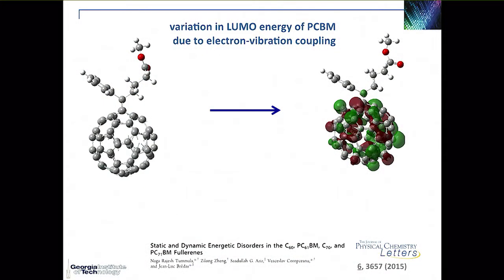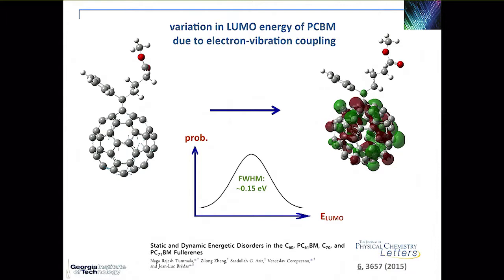Well, those molecules vibrate. Even if you go to 0K, you get a very significant vibration. And because of those vibrations, there are some of them that couple very strongly with, for instance, in the case of PCBM, the LUMO level. And just because of the vibrations that you cannot avoid, and actually the situation is not much worse at 300K, room temperature, than it is at 0K, you get a fluctuation in the HOMO or LUMO levels that can be as large as a full width at half maximum of 150 millielectron volts, which is very significant in the context of what we are talking about.